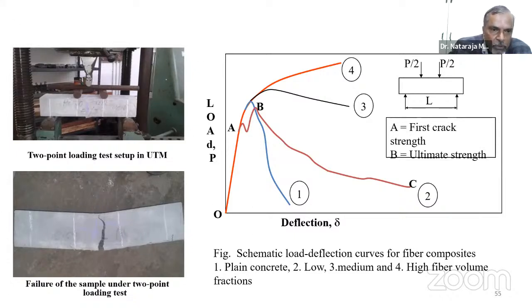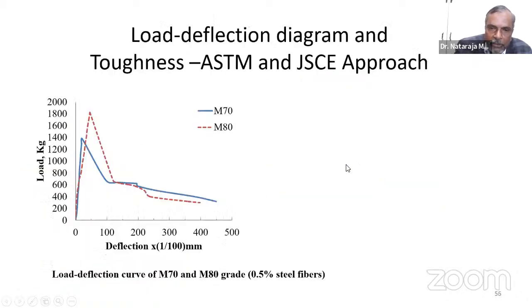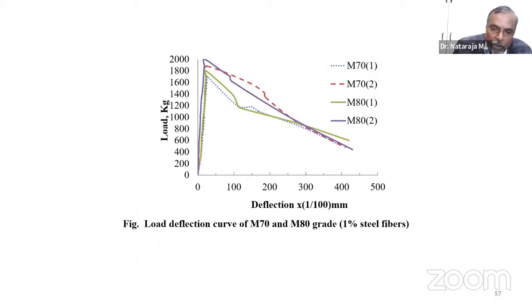And this is the setup which we have used in our laboratory. And this is the behavior for the normal concrete, my dear friends. The moment you add the steel fiber, the drooping behavior becomes like this, and there is a tremendous area under the drooping portion. That is where the enhanced ductility and energy absorption capacity come from. And these are the typical graphs which we have got for M70 and M80. And kindly see that for M80, the area under the curve has definitely increased, and that is where the toughness of the concrete comes from. And again, for 1% fiber.